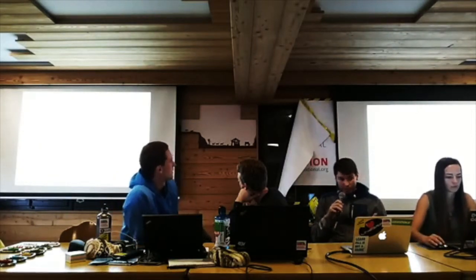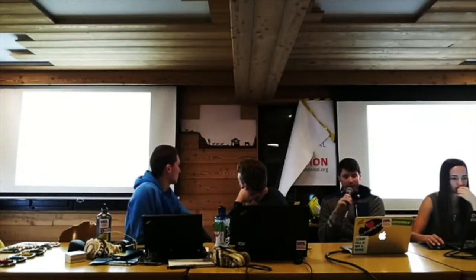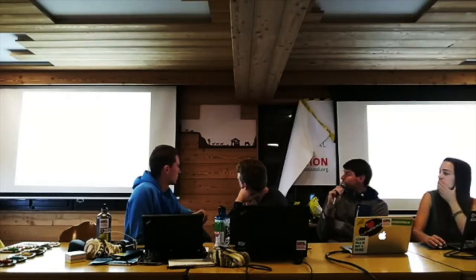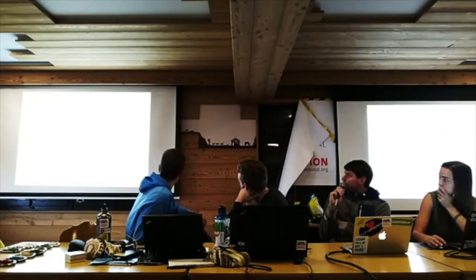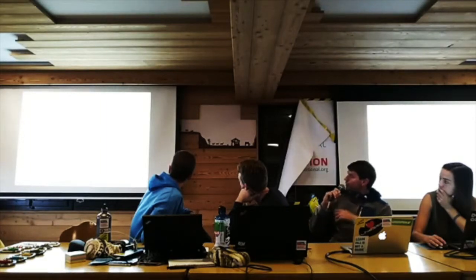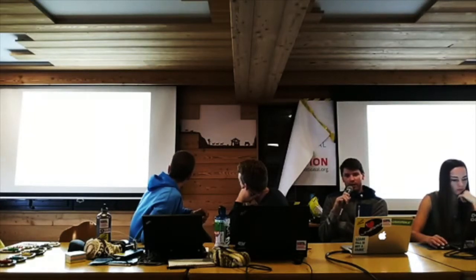Is this just a scientific scenario? Is this just an urban myth? So I tried to find some studies about this, and I found this very useful graphic. This is the molecular picture of an aluminium surface. And we can see here what happens if some stress and some cracks are applied to the left side of this surface. These two molecules on the left side, if they are damaged, are enough, and they are called stage 1 fatigue cracks. It's just about 1/100th or 1/1000th of a millimeter deep, and it's enough for starting further fatigue cracks.